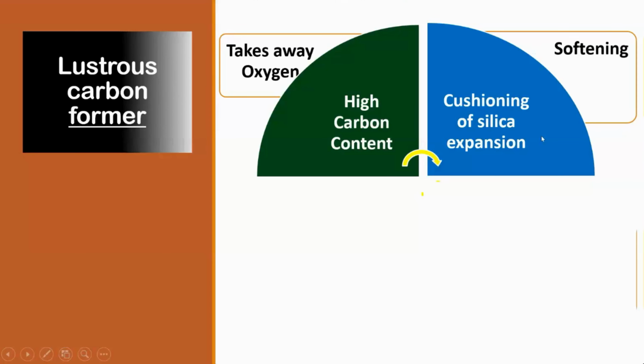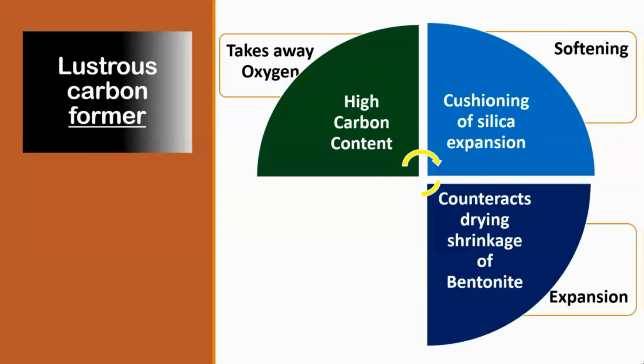Silica, when silica is the sand that you are using, due to heat, it is going to expand. So to counter this, there has to be something to absorb the expansion forces. So the lustrous carbon former will have to soften also. And then when it becomes a coke, coke occupies more volume. So the same lustrous carbon former, it softens and then it expands while becoming a coke. And that coke is going to counteract any shrinkage effect of the bentonite.